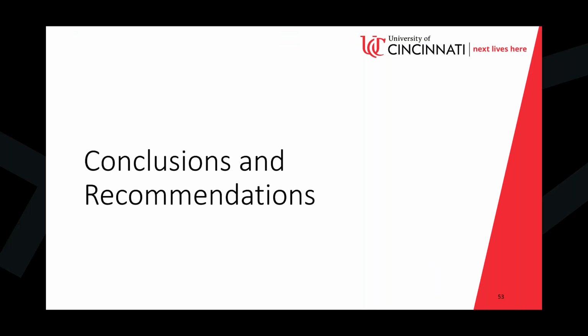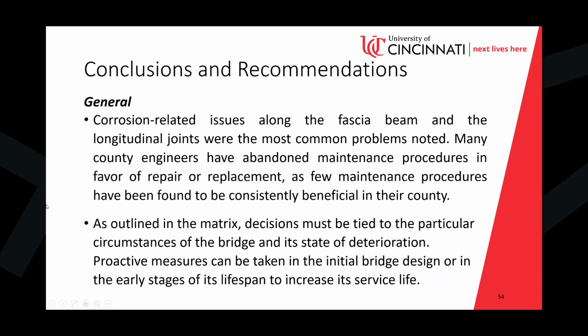In terms of conclusions and recommendations, general conclusions, we found that the corrosion-related issues really occur primarily in the fascia beam and the longitudinal joints. Many county engineers have kind of abandoned maintenance procedures in favor of repair or replacement, kind of wait until the problem just becomes so big that you have to replace it. But hoping with this matrix, there might be some opportunities to be a little more proactive and take measures earlier on. We feel that proactive measures early on in the initial bridge design or early stages of the lifespan of the bridge can increase its service life.